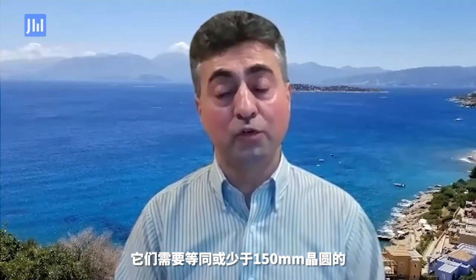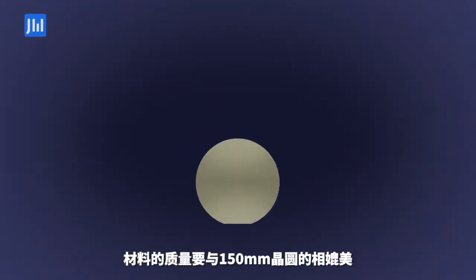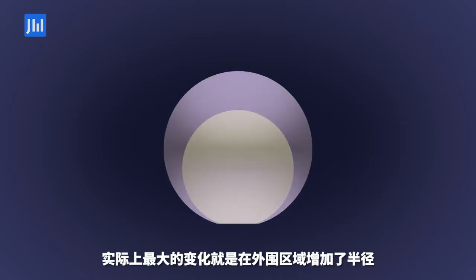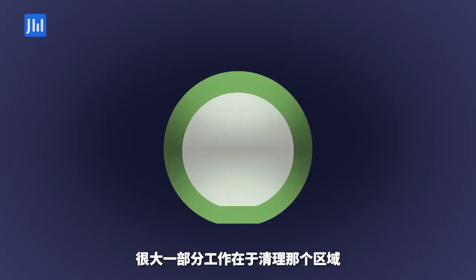The first thing is that the number of defects per centimeter square on the 200mm wafer needs to be comparable or lower to those of the 150mm wafers. So basically the quality of the material when you go from 150mm to 200mm needs to stay the same. And a lot of the work in releasing 200mm wafers is in making sure that the defect density, the quality of the material, is similar to what you have at 150. And remember, when you go from 150 to 200, it is really the area in the periphery where you're increasing the radius that contains a lot of the defects. So a lot of the work is to clean up that area and make sure the yields are good and comparable to what you have at 150mm.